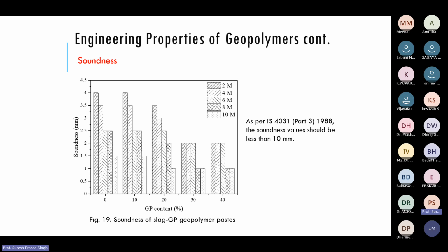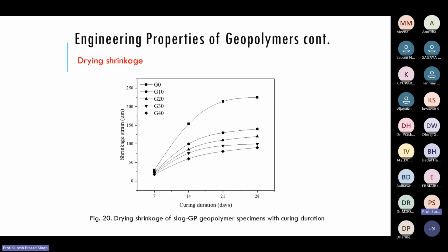So it is within the permissible limits. Then drying shrinkage, again, if you increase the glass content, the drying shrinkage value reduces at the different curing days starting from 7 to 28 days. So it has less shrinkage value compared to the OPC, this slag. This highlights the use of glass powder, replacing a part of slag by glass, soda lime glass.